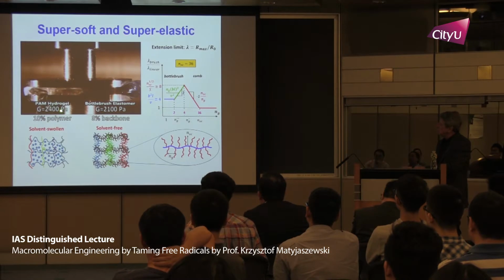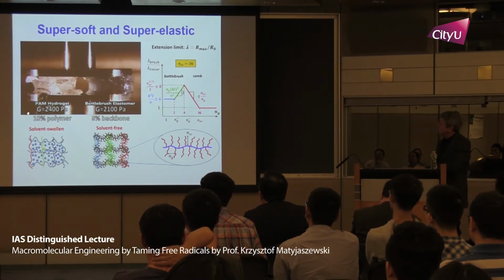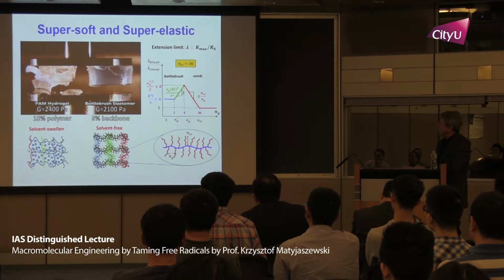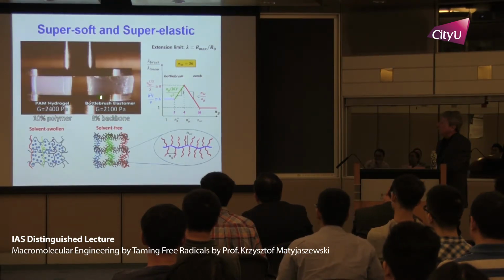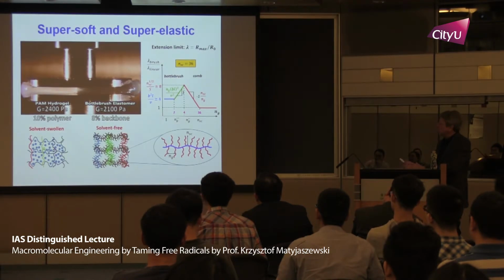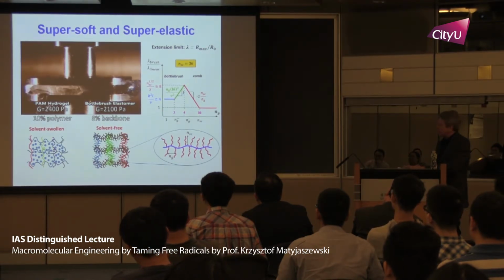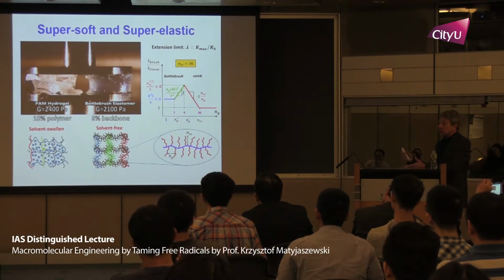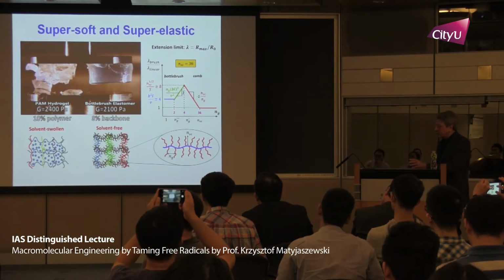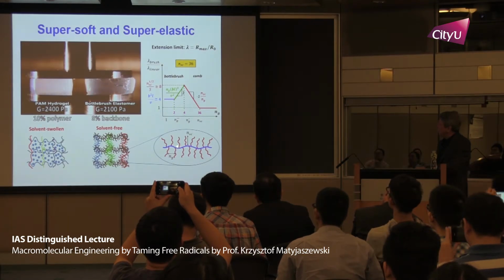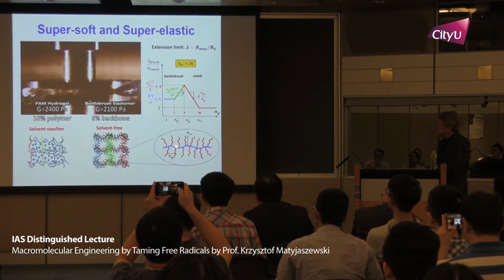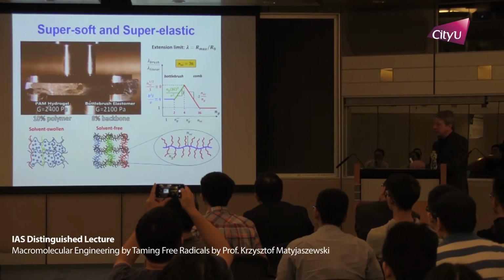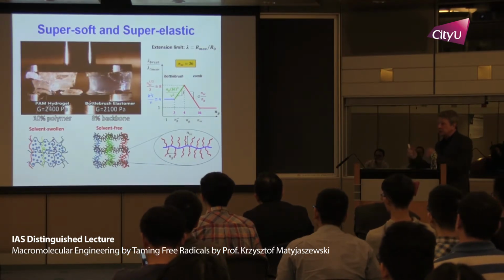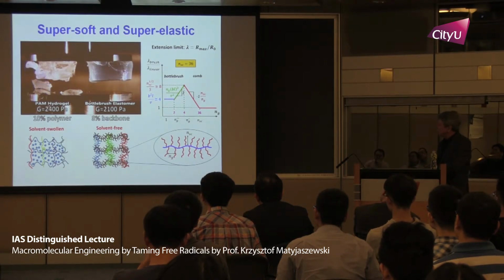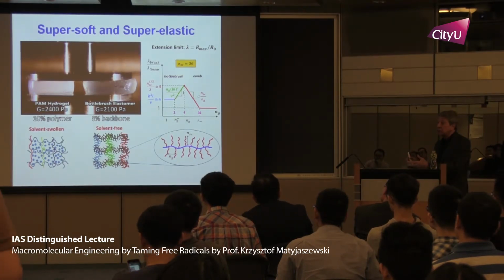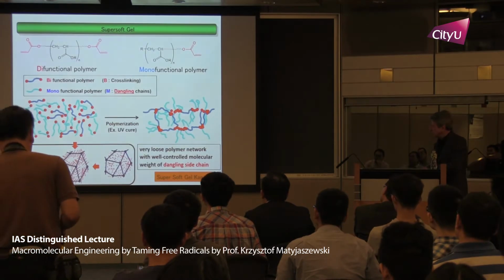This is an example of a hydrogel. This is 10% polymer network, 90% water. This is 8% backbone, 92% side chain. And you could see how dramatic the difference in properties is. This is in fact very brittle, although it's 90% water. So there are a couple of parameters which are important. One is the length of side chains. The other one is also graft density. If you graft too dense, they have too much tension, they can also break. So we control this graft density, and we also control the crosslink density to make them optimal.